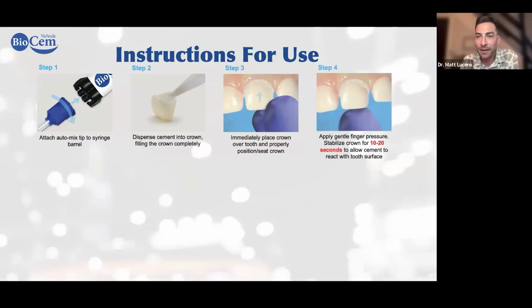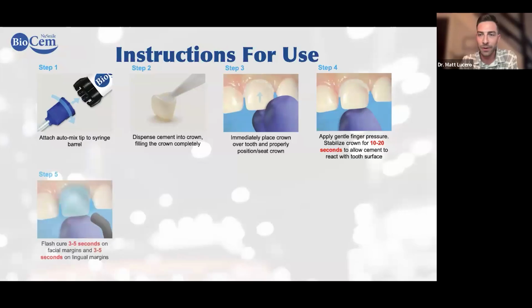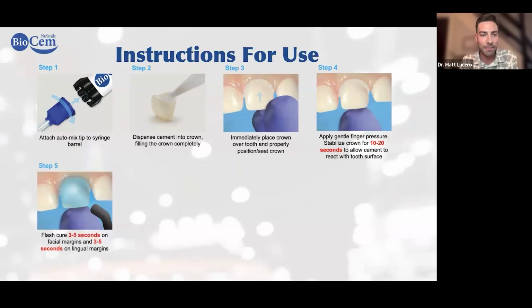But the one difference with BioCem is you have to wait about 10 to 20 seconds once you seat that crown. For most of us, it's not a big deal because we're aligning the crowns and we're fixing rotations and cants and things like that. But that 10 to 20 seconds allows that cement to start penetrating the dental tubules, and that's where you're going to get your bioactivity from. If we cure it too quickly, then we don't give that material a chance to get into those tubules. So that 10 to 20 seconds usually doesn't make too big of a difference because we're kind of goofing around with the crown anyway, but that allows that bioactivity to take place.